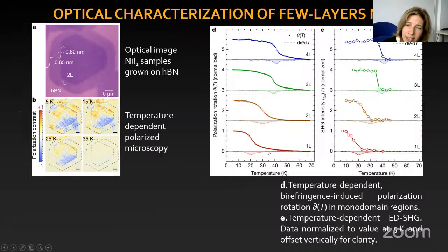They were studying the signal obtained in one monolayer, bilayer, 3-layer, 4-layer, and bulk. What they observed was that there's a signal which is not zero, and the temperature at which this signal emerges decreases if you go from bulk to one layer, but still, even at the monolayer level, you get some signal. So it orders somehow, even at the monolayer level.